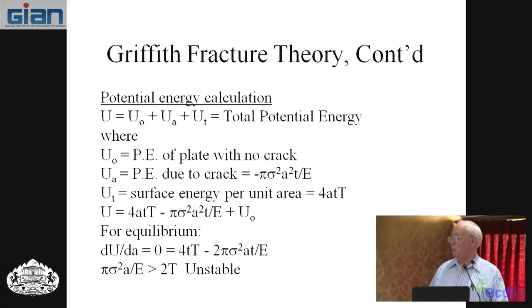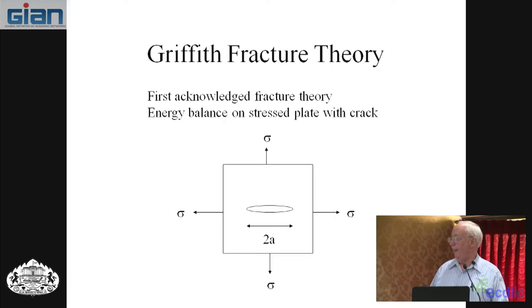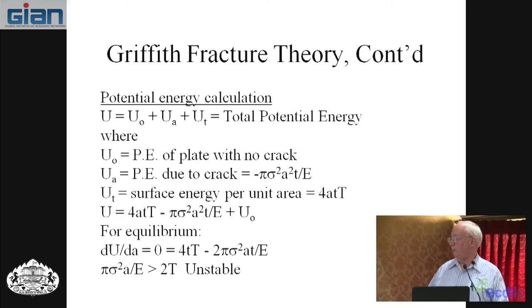UA was potential energy change due to the introduction of the crack, the 2A crack. And this solution came from an elastician named Inglis, and said this is really what would allow Griffiths to develop his theory. Anyway, sigma is stress, biaxial stress. A, of course, is the half defect size. T is the thickness of the plate, and E is elastic modulus. So all those terms come in.